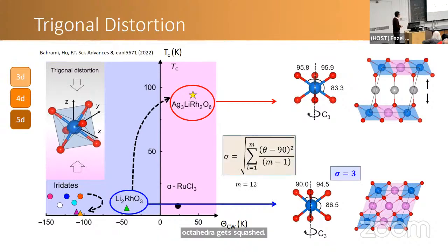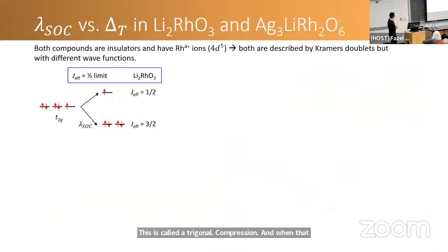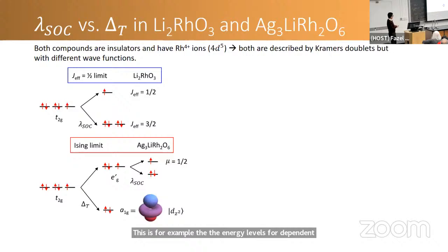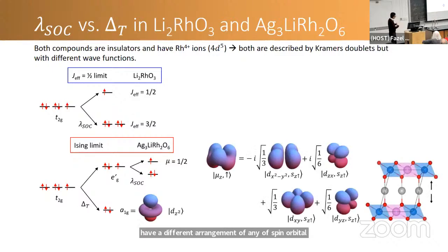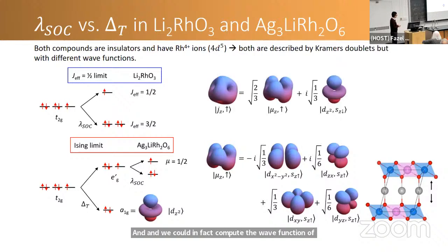And when that happens, we can, of course, characterize it, and the spin orbital arrangement of the material changes. This is, for example, the energy levels for the parent compound lithium rhodate. But here is a different one. You have a different arrangement of spin orbital levels for this new material, silver lithium rhodate. And we could, in fact, compute the wave function of this new material, and we found that the wave function in this exchanged material is different from its parent compound, in that it has a trigonal symmetry as opposed to the cubic symmetry in its parent compound.